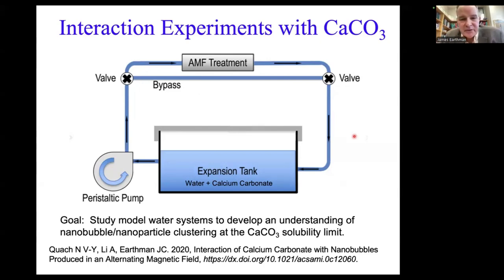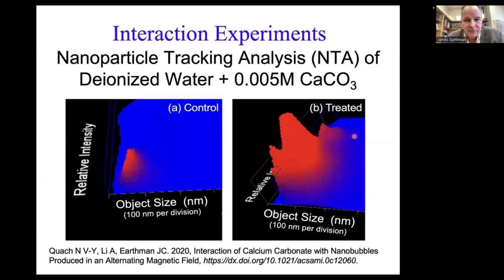So we wanted to test this in a basic research study, and we used an instrument called a NanoSight. It's another scattered light system that you can measure nanoparticles and nanobubbles together. The nice thing about this NanoSight is it also gives you the relative intensity of the scattering center that's producing the light. So it can not only measure its size, but it also can measure the intensity of the light coming from it. If we take deionized water and just put calcium carbonate in it, we would get one peak in the object size. This is at the solubility limit of the calcium carbonate, very low, 0.005 molar.